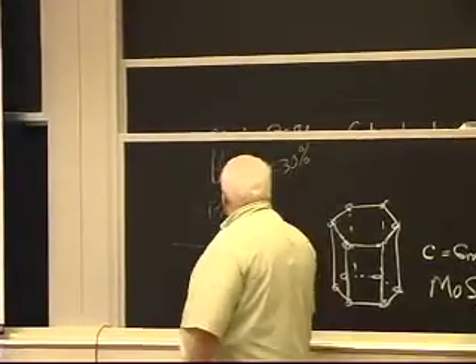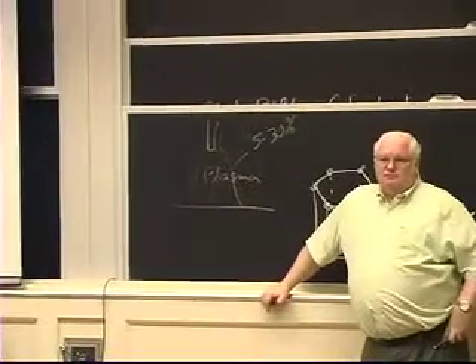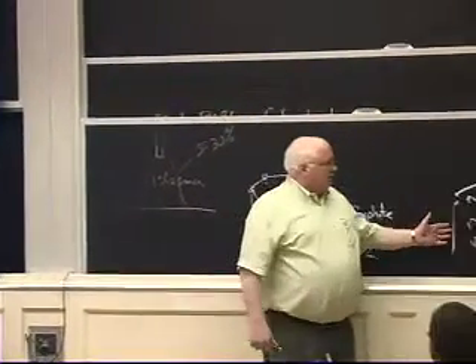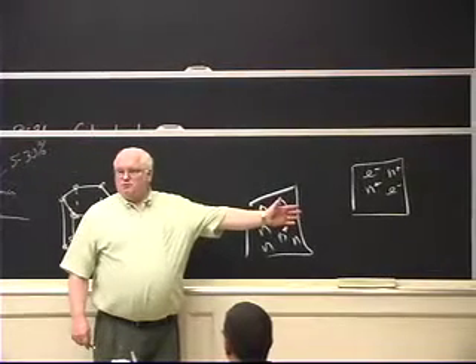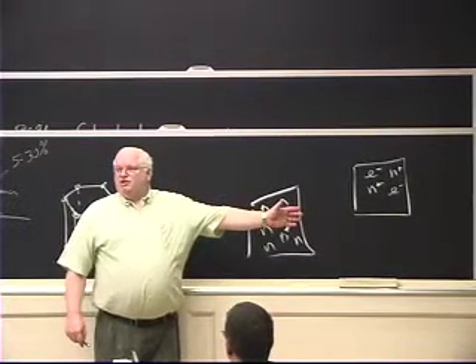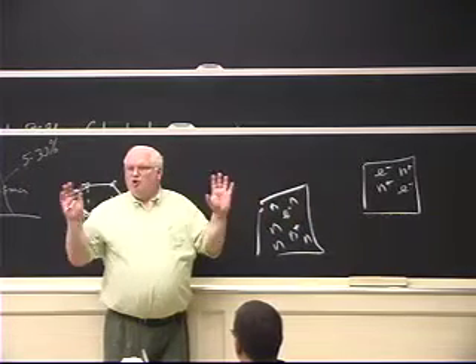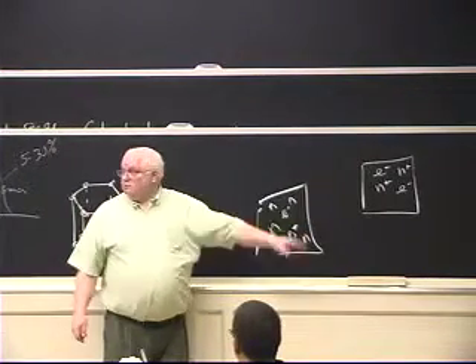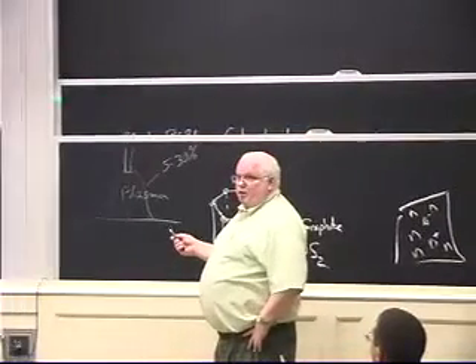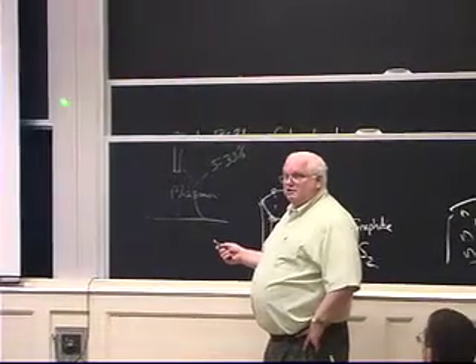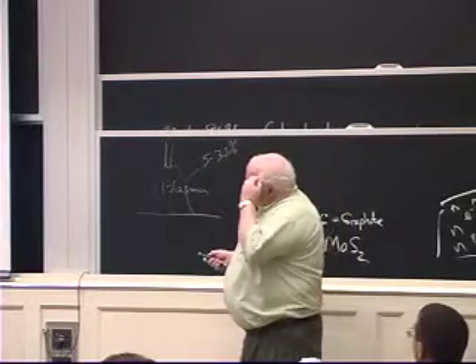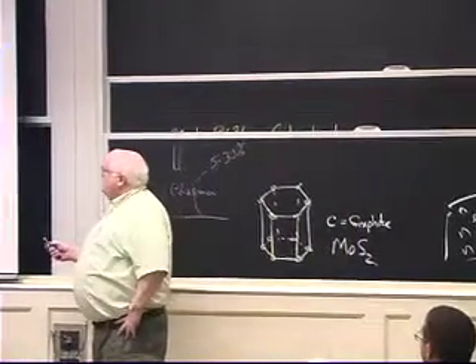Now if I go back and look at the mobility of the electrons in here, I can calculate that in order to run typical welding arcs, I need between 5 and 30% ionized. Okay? That is not weakly ionized. It's not fully ionized. It's a partially ionized plasma. Okay? The physicists don't want to touch this with a 10-foot pole. They'll much rather work on tokamaks and things like that. Tokamak is a fully ionized plasma. I mean, in tokamaks, you're trying to get out of here where you strip all the electrons off. Okay, hundreds of thousands of degrees or millions of degrees Kelvin. You're going way out here. But this practical area back here for welding, no one wants to touch.